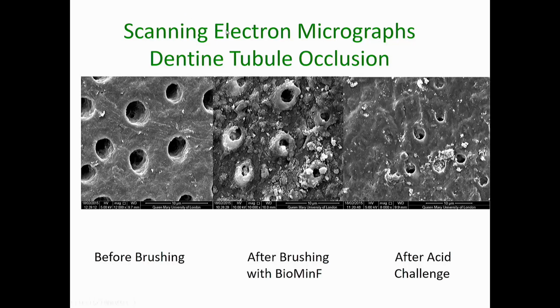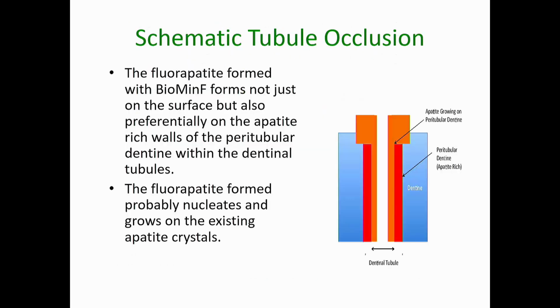When we give it an acid challenge, which is citric acid to mimic the consumption of a sugary drink, you can see that quite a lot of this surface apatite and these little glass particles are dissolved. And some of the apatite, the fluorapatite that's dissolved, reprecipitates. So we actually look to have better tubule occlusion after the acid challenge. With the other toothpastes that form, for example, hydroxycarbonated apatite or occlude the tubules with calcium carbonate, those species disappear when given an acid challenge and the tubules reopen. So the fluorapatite gives us much better, durable tubule occlusion, particularly under acidic conditions.